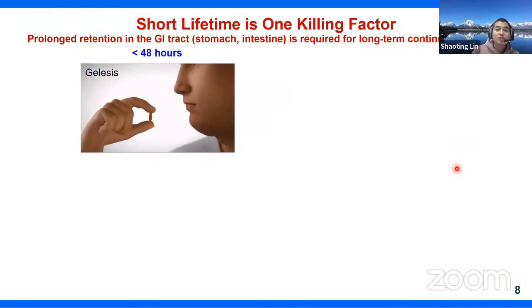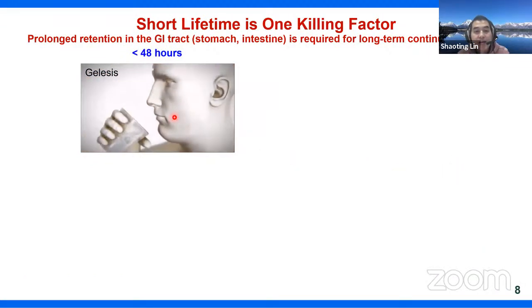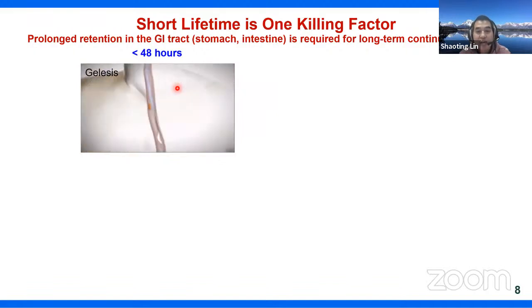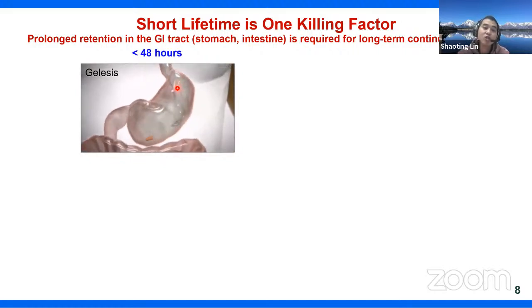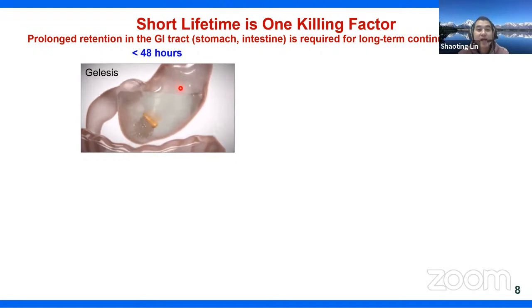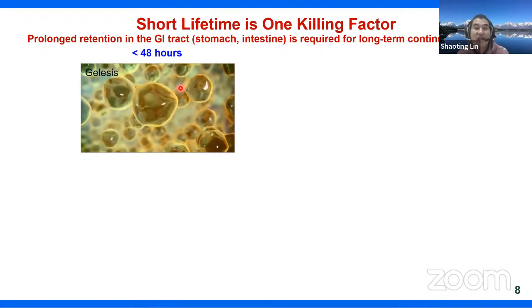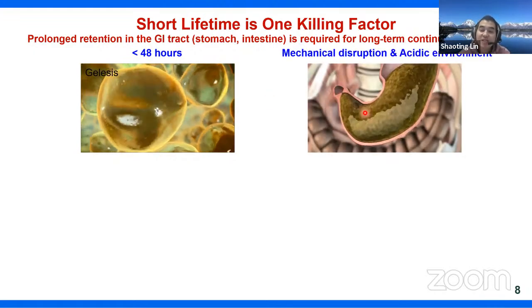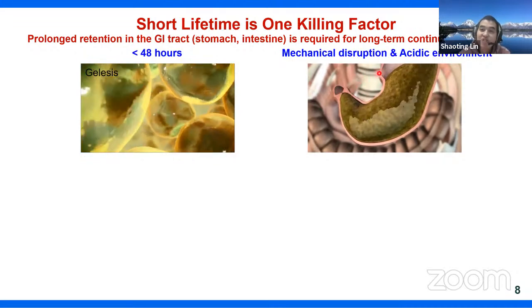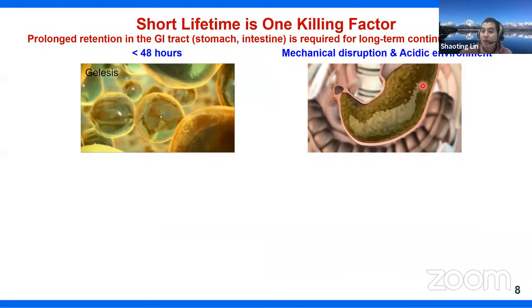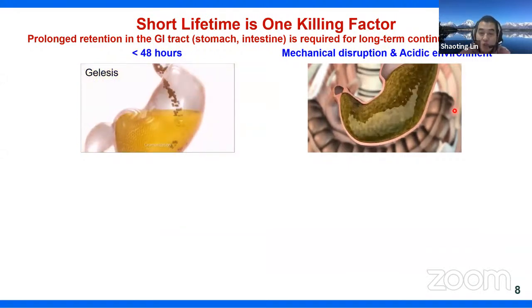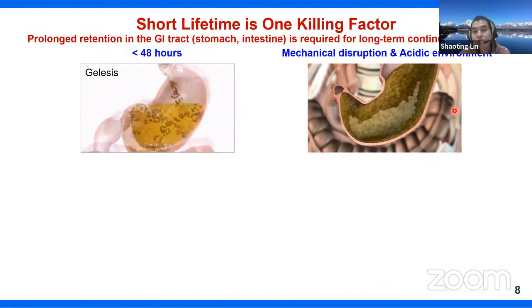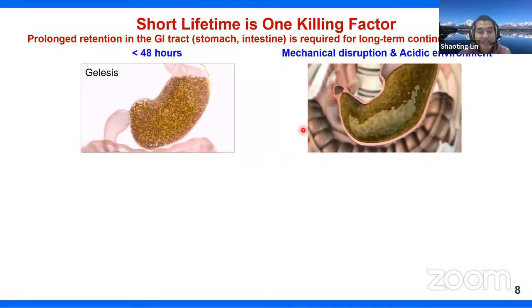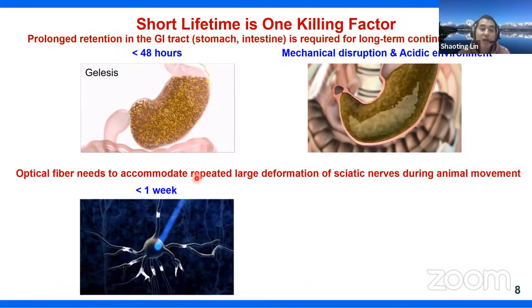Here are two specific examples. The first example is the ingestible hydrogel pill. Currently, the lifetime of a hydrogel-based gastric retentive device is typically shorter than 48 hours. And the short lifetime is mainly attributed to two factors. The first factor is mechanical disruptive force, and the second one is the severe acidic environment produced by the human stomach. My mission is to enhance the mechanical properties so that we can possibly extend the lifetime of existing gastric retentive devices.